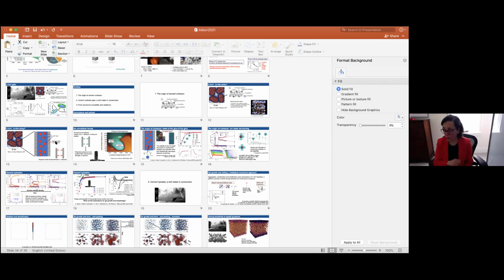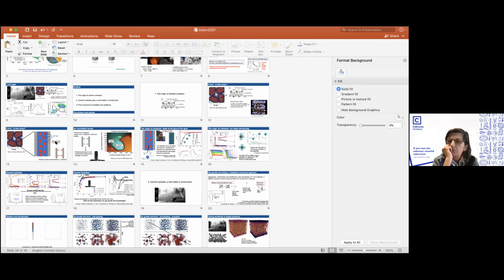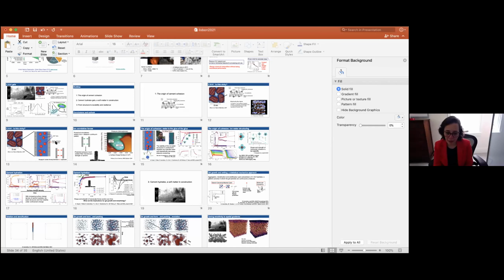I don't mean to say at all that surface heterogeneities are not important. For example, we found that the arrangement of the ions, of the ion-water structure that we obtain, is a lattice that is completely anti-registered with the lattice in the other layer. And it's very similar to the ground state found by our theory colleagues, who were just looking at the electrostatic problem with just the ions between surface charges in this very strong coupling regime, which suggests again that the electrostatics is what becomes dominant at that point. But certainly the presence of surface heterogeneities will change where your lattice gets stuck, right? And it can create pinning sites. So there are a lot of interesting things to understand there.